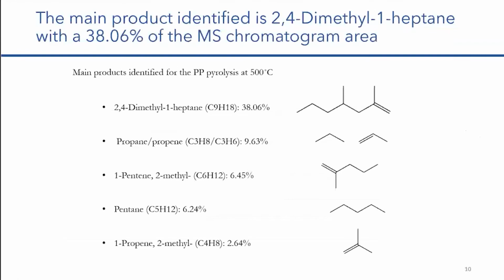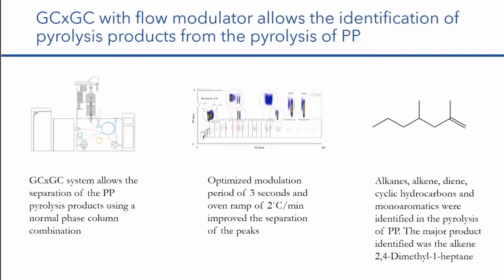The main products identified are C9, propane, so C5, C5 and C6 products, and so on. Finally, with all these results, we are able to separate the product distribution, the products from the pyrolysis, using a column combination where the first column separates by boiling point and the second by polarity. Then we have optimized the modulation period using 3 seconds and an oven ramp of 2 Celsius per minute, and we have identified alkanes, alkenes, and dienes.